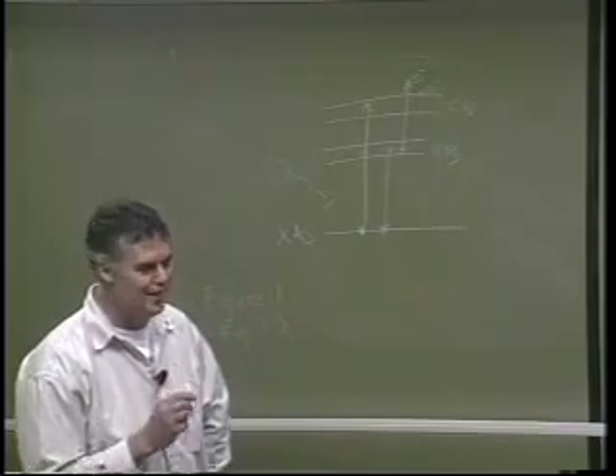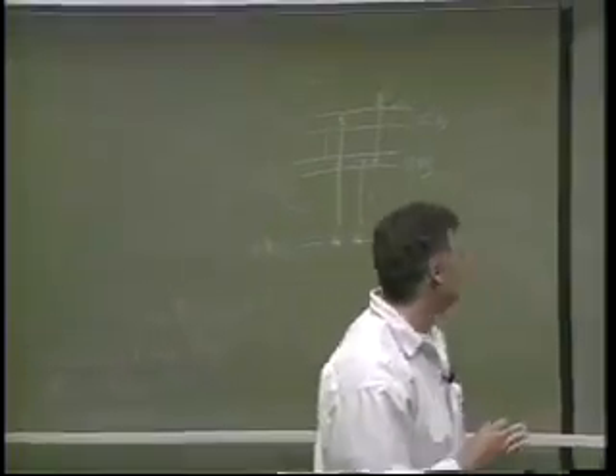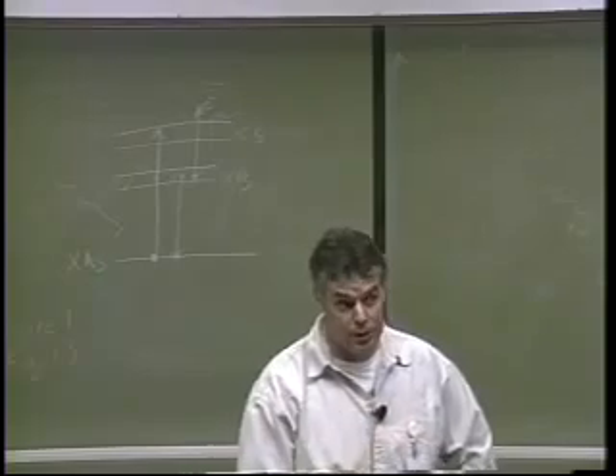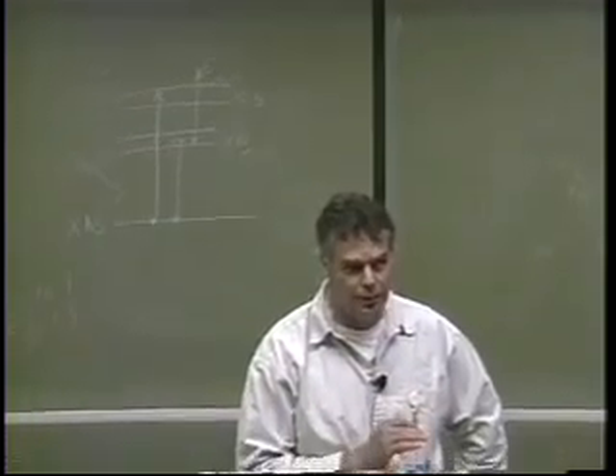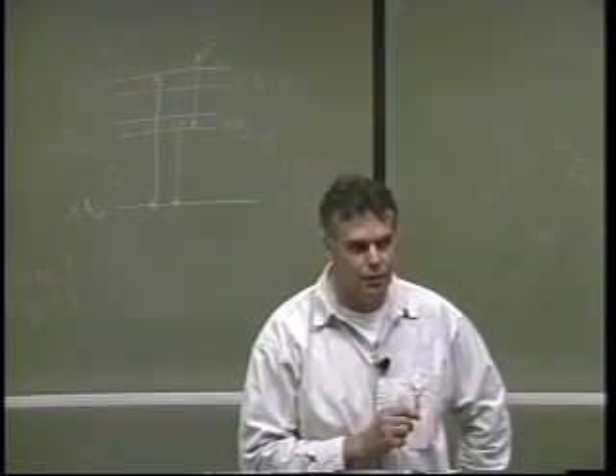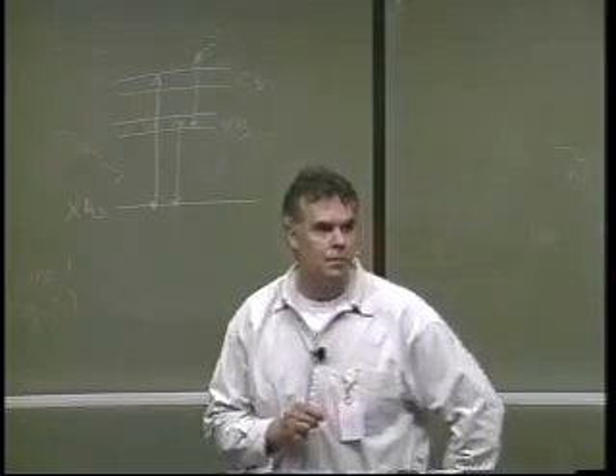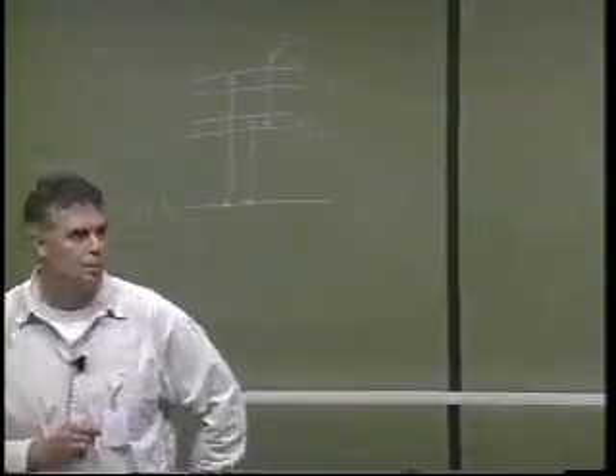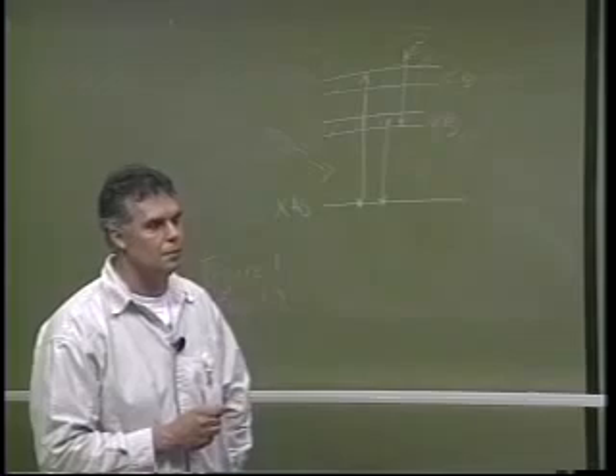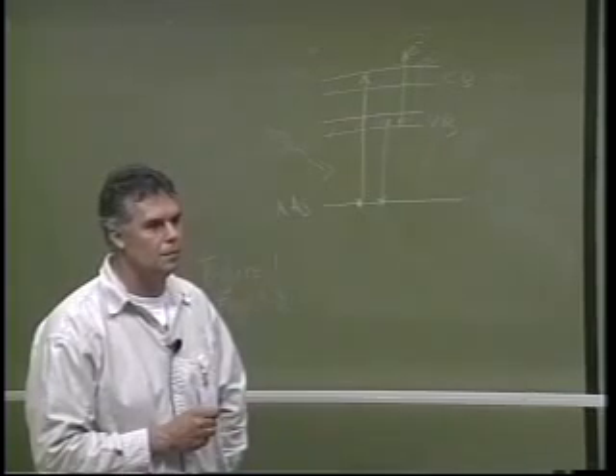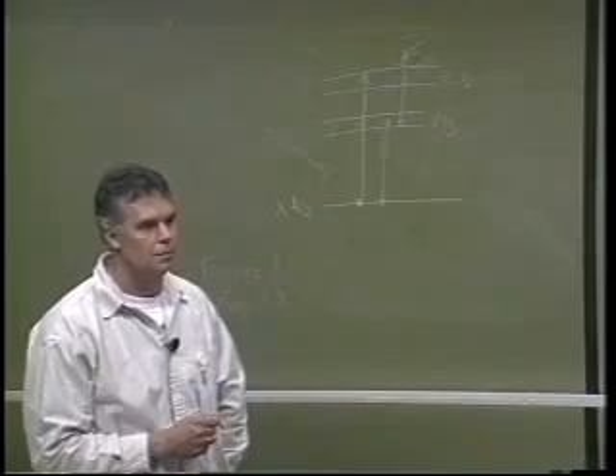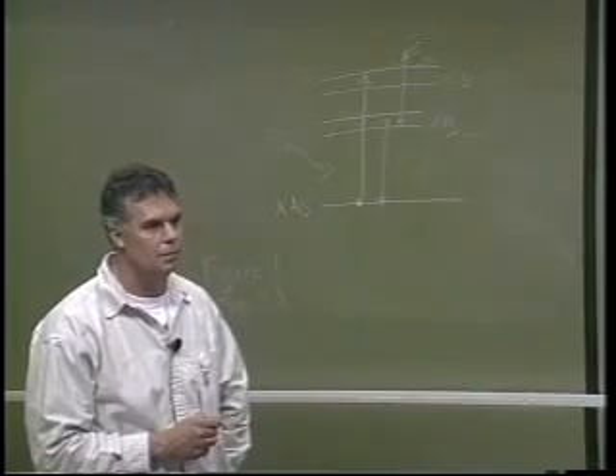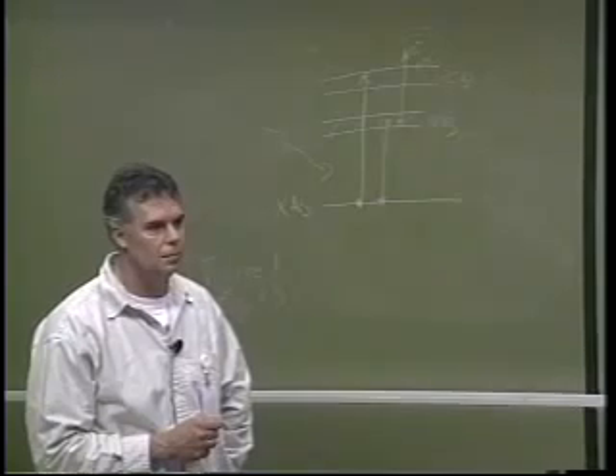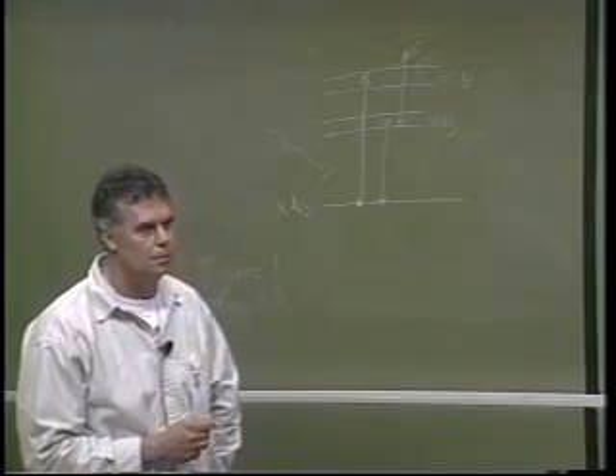Let's make sure I get the question right. You want me to compare the fluorescence yield to the electron yield, and why is that different? Well, give us the physical model. We've seen the curve, so we know for low Z you get one, and for high Z you're more likely to get the other, but we don't really understand why, when there's a vacancy, let's say a K-shell vacancy, what drives an Auger process? Why would that be more important than the emission of a photon?